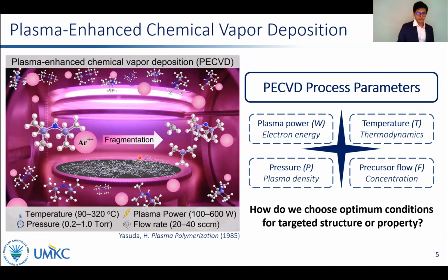For a reactor configuration, there are usually 4 major process variables: plasma power, which affects the energy available for gas-phase reactions in plasma; temperature, which affects the thermodynamic reactions happening on the substrate surface; pressure, which indirectly affects the plasma energy and plasma density; and precursor flow, which defines the reactant flux of the precursors in plasma, thereby controlling the kinetics of this deposition.